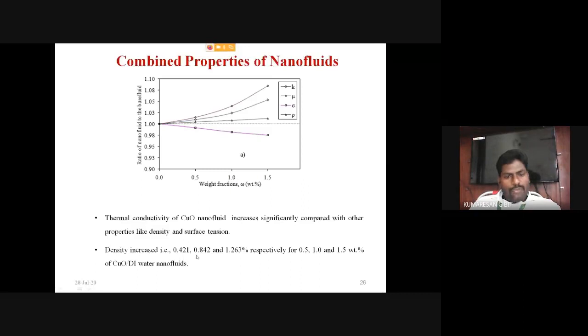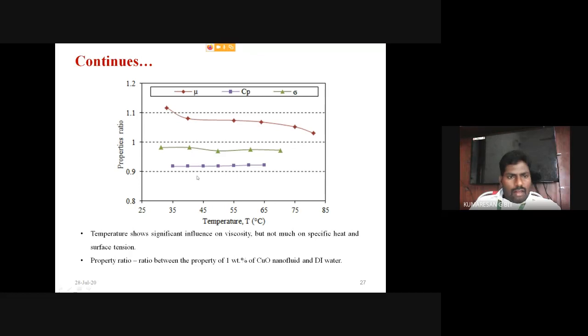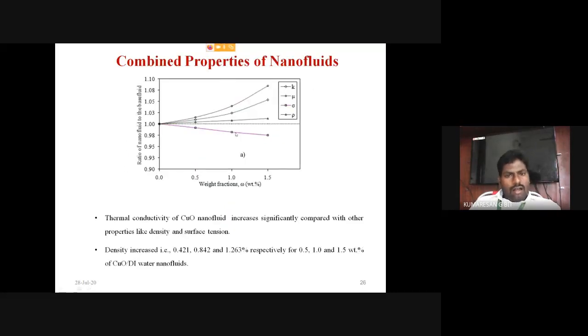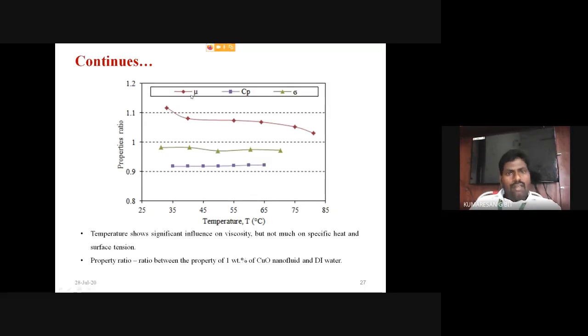Then density increases about 0.421, 0.842 and 1.263% for 0.5, 1 and 1.5% of the CuO-DI water nanofluid. Then this is the same combined property analysis conducted with respect to increasing temperature, and you see here dynamic viscosity, specific heat and surface tension properties are analyzed in this graph. Temperature shows significant influence on viscosity but not much on the specific heat and the surface tension value. That means you see in the first, this red color indication, that the dynamic viscosity of the working fluid gradually reduces with increasing temperature, but the specific heat and the surface tension, these two properties, are not majorly influenced by the temperature. With increasing temperature, these properties are not varying.